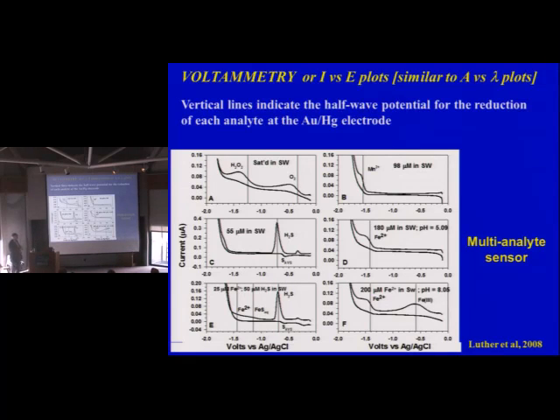So here you can take a look at manganese in seawater. Here's iron in seawater. We now add sulfide and iron together, and you actually start getting another peak due to FeS nanoparticles in addition. So here's your iron, and here's your manganese. You notice that sometimes the shapes are a little different, aren't they? The manganese is sharper than the iron. And what you're doing is reducing manganese 2 to manganese 0 in the amalgam, and the iron 2 to iron 0 in the amalgam. Iron's harder than manganese, so it doesn't form as good a film as manganese. So what happens is you get a little different signal. If you take iron 2 and put it in slightly oxygenated water, notice there's no peak over here.